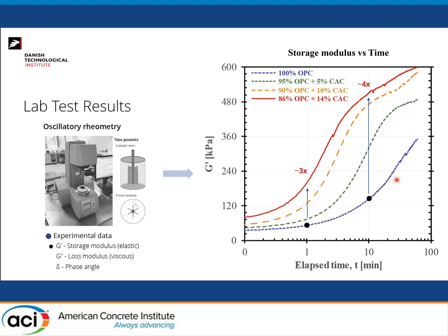And then as we increase the dosage of calcium aluminate cement in the system, you have a heavy formation of precipitation of ettringite, and that enables the material to have a higher slope in the structural buildup, and of course a higher elastic contribution, a higher G value over the first 10 minutes. So the order of magnitude in the gain of G prime for the mix activated with 14% of calcium aluminate cement by weight of cement is about 4 times. So that means that within 10 minutes you have a substantial gain on G prime. Within the first minute there is about 3 times.